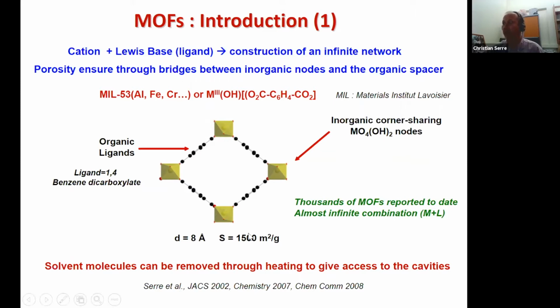And this is one example of a typical benchmark MOF called MIL-53, a trivalent-based metal dicarboxylate solid. The ligand is a benzene dicarboxylate ligand. And then the inorganic part is chains of corner-sharing metal octahedra. So this is one example. Of course, you need to remove the solvent to have porosity, and then it leads to micro and mesopores and variable surface area that can be in some cases record.